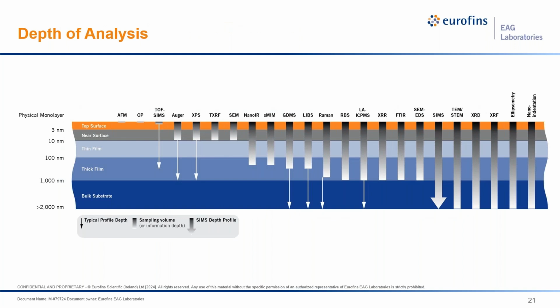Here in this chart, we demonstrate that we have multiple solid sampling analytical techniques that have different sampling depths. This useful chart shows the depth of analysis of each technique. For instance, time-of-flight SIMS has a very shallow sampling depth of only a few nanometers. XPS and Auger analysis depths are 10 nanometers.